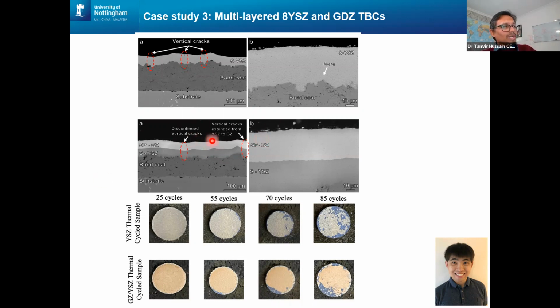So it produces quite different types of microstructure. We were examining how a double layered system compares against a single layer system in a thermal cycle test, which is the most aggressive sort of testing that you can do. You heat things up to 1200 degrees Celsius, cool things down very rapidly, and see how long it takes for 20% of the coating to fail.